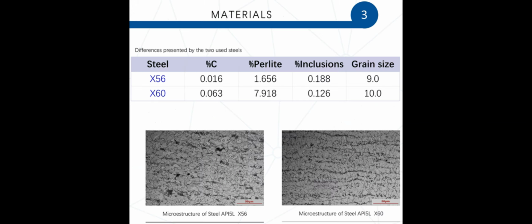Well, as I said before, the most important thing in this work was to evaluate the microstructural differences that can make a material susceptible to SCC. So the materials used were extracted from decommissioned pipelines. After metallurgical and mechanical characterization, the main differences between them were identified, which served to analyze the results of this research.